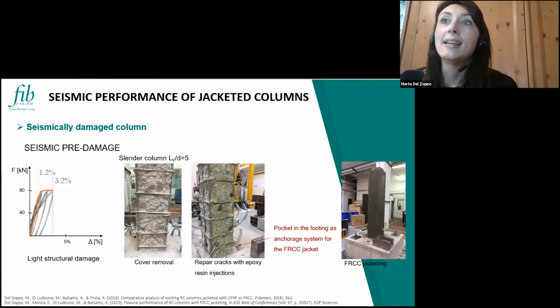And finally, the last application is to show how the jacket can modify the performance of seismically damaged members. So in this case, the same flexural columns that we have seen for the first application have been pre-damaged with this input. So basically, we achieved a 3.2% of drift. And then we applied the jacket. So basically we repaired the specimen because of course it was damaged.